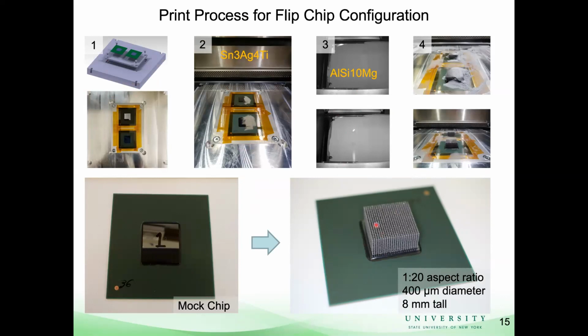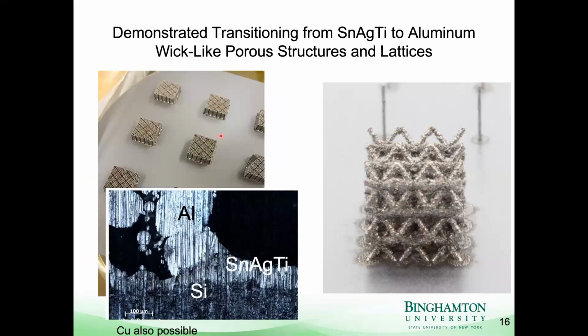This is showing that we could print very narrow features. These are 400 micron diameter pin fins that are 8 millimeters tall. So it's a very high aspect ratio that we could do. We've also printed a lattice structure, with 1 millimeter struts. And this is a wick that we've printed as well. We can print wicks. And this is a microscopy image of the interface. There's some artifacts here from the polishing. These lines here are from the polishing.